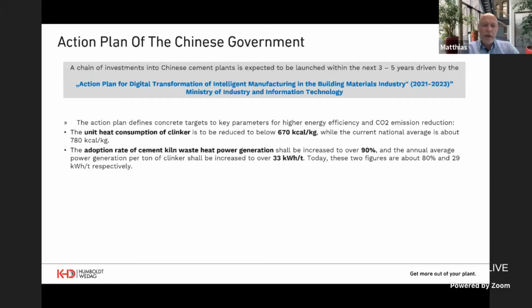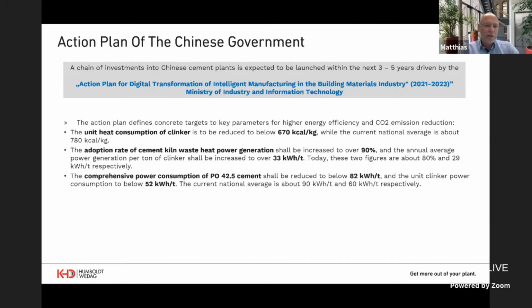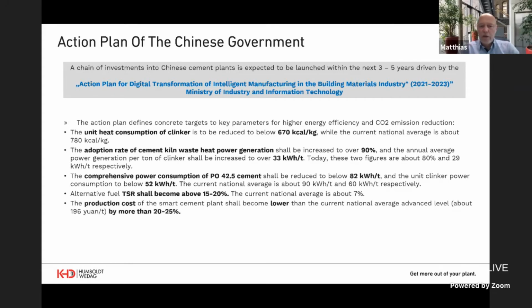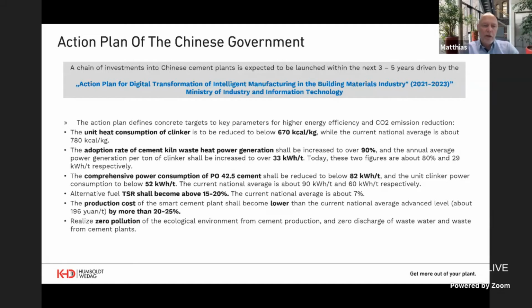Also, this program sees that the adoption rate of cement kiln waste heat power generation shall be increased to 90%. So waste heat recovery systems need to be installed in the Chinese cement plants. At the same time, the electrical energy consumption for grinding must be reduced. And the alternative fuel firing rate, the thermal substitution rate, shall become above 15 to 20%, while the current national average is about 7%. The production cost of cement shall also be lowered by the introduction of artificial intelligence and optimized production operation. So zero pollution is at the end of the goals. Zero pollution of the ecological environment for cement production, zero discharge of wastewater and waste from cement plants.